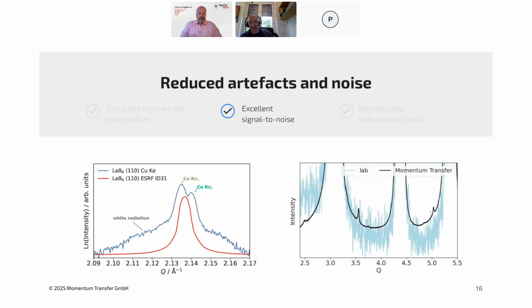And so every peak actually gives a doublet. So you have to model both of those. And because you also have a wider spectrum of white radiation underneath that, you also get a larger contribution to the baseline from white radiation scattering. As compared to our system, you don't have this doublet and you don't have all of this extra scattering from non-monochromatic wavelengths.